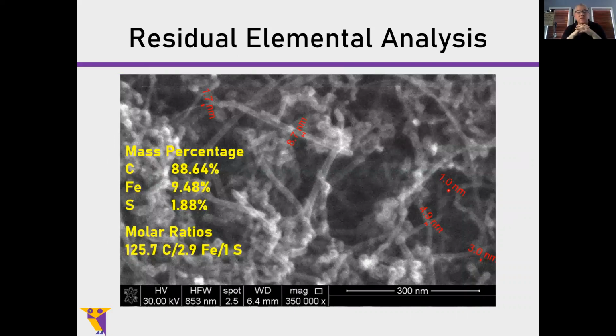Now here's something else that's interesting, and we can take a look at this. This is a species I made, and you can see these little balls. I said we would come back to them. What we're seeing here is nanotubes, and you're seeing those little balls of metal around there. Now, you do an elemental analysis, you find that about 90% is carbon. About 10% of this is iron, and there's some trace sulfur, with molar ratios, and you can see that there's probably about 40 times by molar ratio carbon to iron in these things.